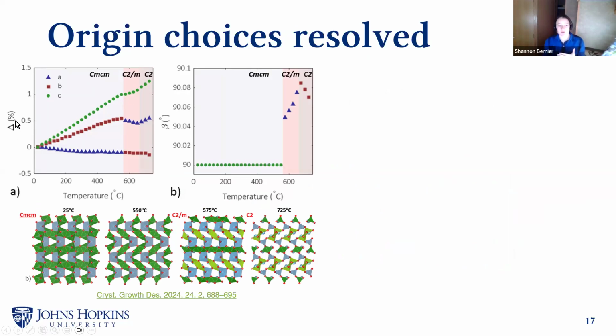These would be the differences in the lattice parameters. So here we're subtracting the initial value of the side lengths from whatever they currently are, and then dividing by that initial value to get a percent change. And you can watch how each individual lattice parameter changes. And then the right-hand plot is just a plot of what the angles are in this system. So it starts out as orthorhombic and everything is 90 degrees, but then it'll go through a phase transition such that 90 degrees is no longer the best angle to describe the unit cell.